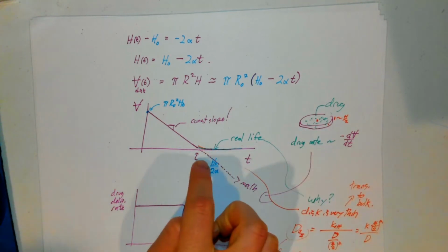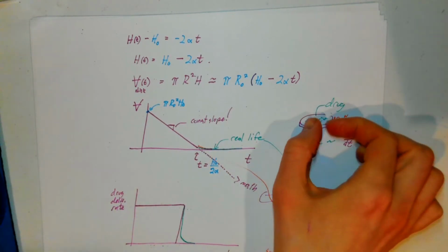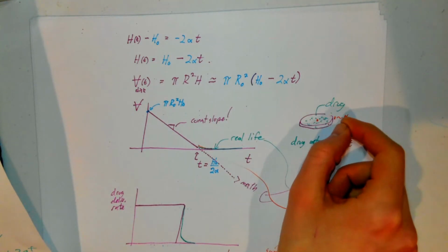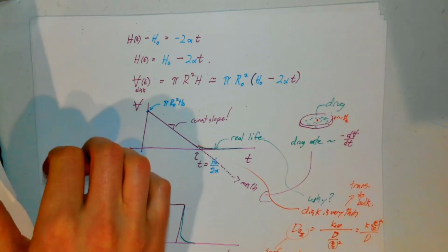The thicker you make the disk, the longer you make this drug delivery vehicle last. Also the more area you give the disk, the faster you can elute drug to the patient. So you can play around with the thickness, you can play around with the radius, you can play around with the chemistry of the ester bonds and how quickly those break. You can play around with the concentration of drug within these things.